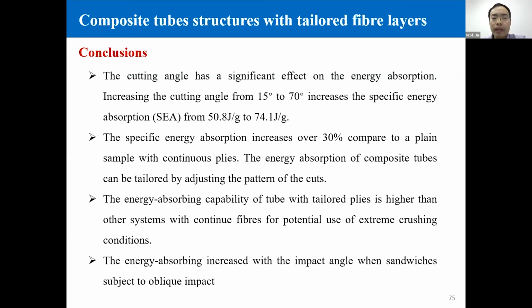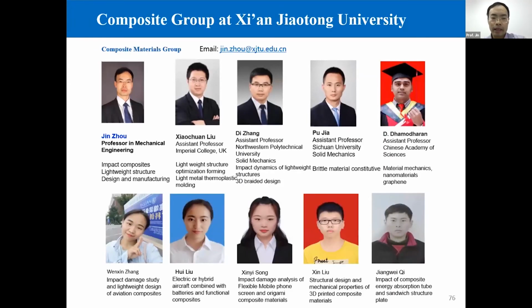The cutting angle has a significant effect on energy absorption. By increasing the cutting angle up to 70 degrees, we were able to increase the energy absorption up to 74 kilojoule per kilogram. And the energy absorption with tailored composite layer is higher than the plain composite tube with the continuous layer. And we also noticed that the sandwich structure at a high oblique impact is able to absorb more energy.